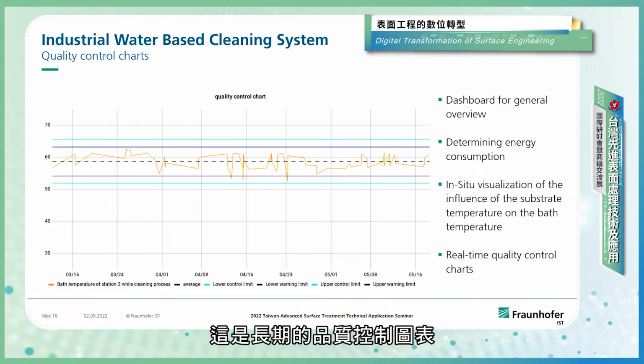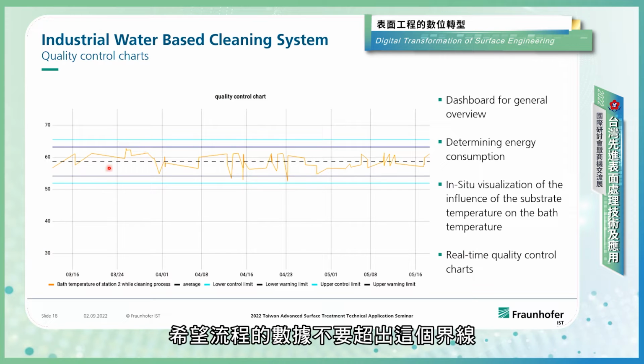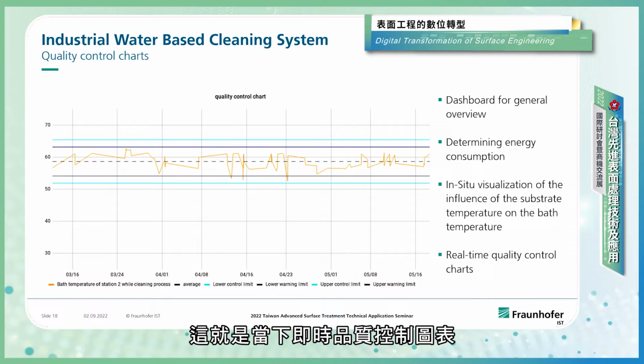We get quality control sheets on the long term. Here you can see an example over a period of 2 months, determining the energy consumption. We can see the bath temperature. We have a corridor where we want to stay within. We have a lower and an upper warning limit, and we have a control limit of our process, and we want to keep our process within a given boundary. And we have access to real-time quality control charts in that situation.